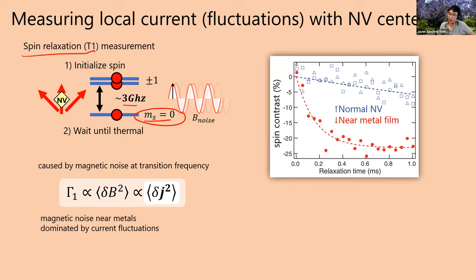decay, okay? So the way it looks is that you start off with a polarized signal, and then you wait some time, and the signal is going to decay exponentially with a characteristic time given by T1, which is 1 over the relaxation rate. All right? And the point is that because this is a magnetic transition, it's dominated by magnetic noise. So magnetic noise is what's going to cause the spin to relax and return to a thermal equilibrium state. And